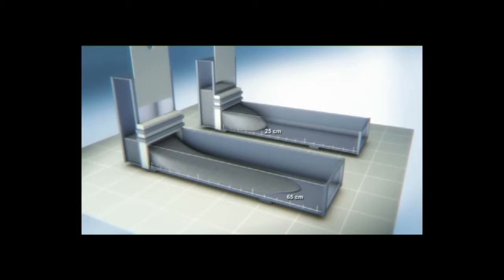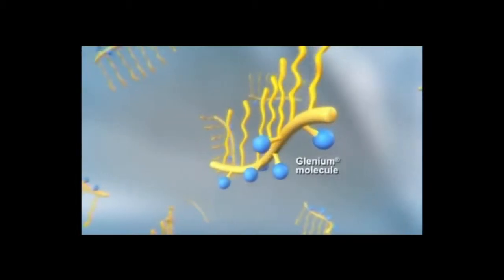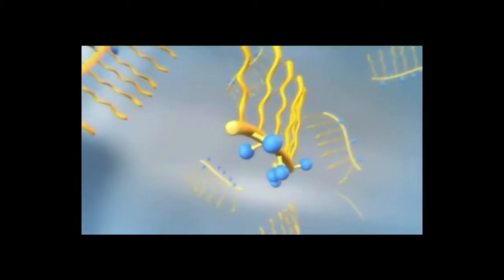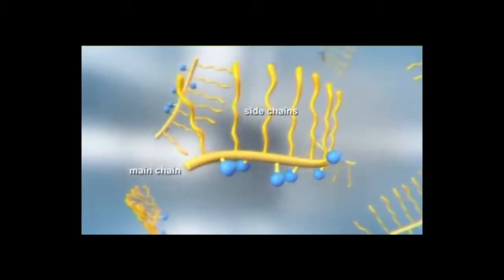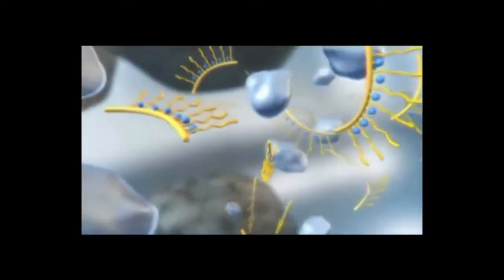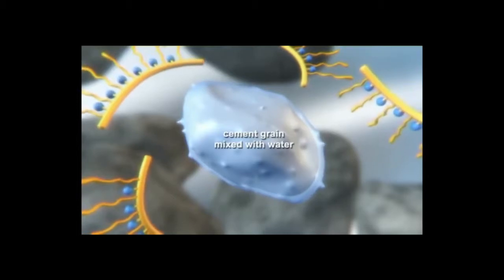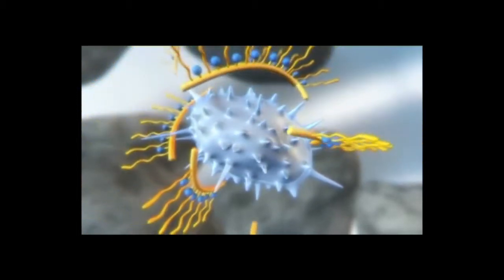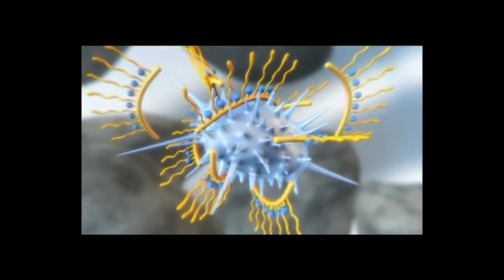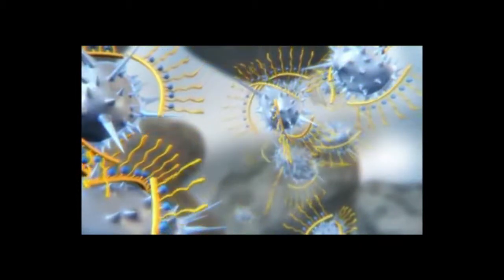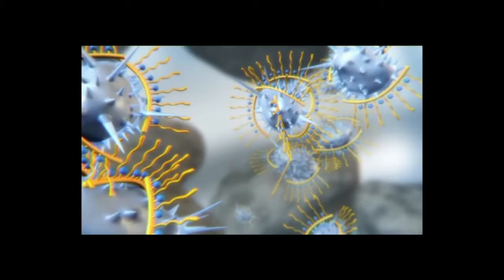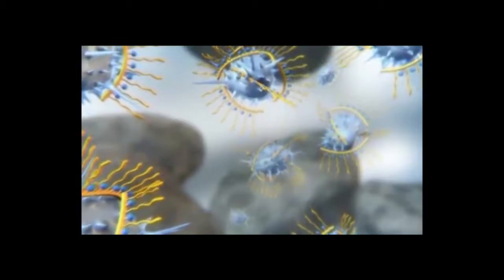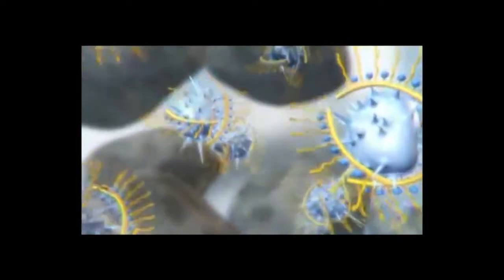Modern superplasticizers like Glenium are based on synthetic organic polymers such as polycarboxylate ether, called PCE for short. A PCE molecule consists of one long main chain and shorter side chains. The main chains are negatively charged. When cement is mixed with water, it reacts and starts to form crystalline needles that interlock with each other to form a hard, rock-like substance. When the PCE molecules are mixed with liquid concrete, they are adsorbed onto the surfaces of the particles contained in the concrete. The side chains of the molecules point outwards, like the spines of a chestnut burr, and hold the particles at a distance to each other. This makes it easier for them to move against each other, and the concrete becomes more fluid. Concrete can be given the desired properties by varying the length of the main and side chains.